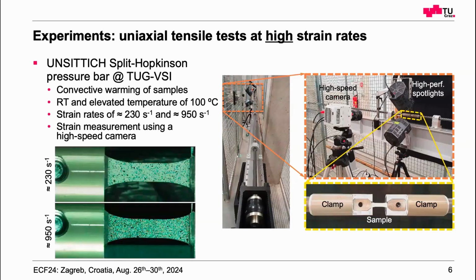After this, we also performed uniaxial tensile tests at high strain rates. Therefore, we used a split Hopkinson pressure bar. And here it was also possible to heat up the samples, but it was only possible to do the test at room temperature and at 100 degrees. And here we performed tests at around 230 strain rate and very fast tests at 950. Sorry, the videos here don't work, but it's not a problem. The strain was measured by using a DIC system with a high-speed camera.